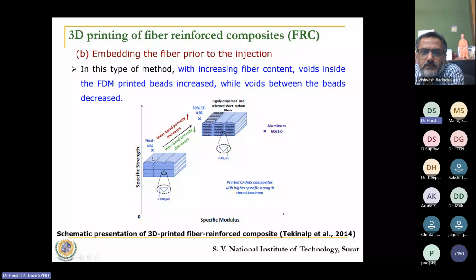So when we compare the neat ABS with the 30% carbon fiber ABS, we observe that there is a good increase in the strength. And this strength is comparable with the strength of aluminum 6061.